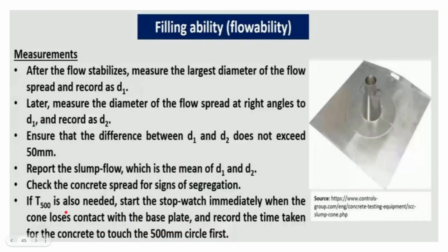Then if T500 is also needed, that is basically the time taken to reach the 500 mm circle. So we need to start the stopwatch immediately when the cone loses contact with the base plate. Just as we lift up, we start the stopwatch immediately and record the time taken for the concrete to touch the 500 mm circle first. So the time from lifting the cone to the time the flow first touches the 500 mm circle is the T500 value. If we are interested, we can check that also.